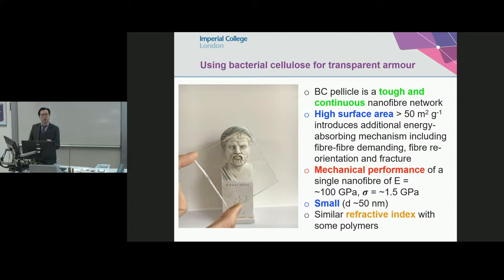And the diameter is small. Why is that good? It's so small that it doesn't interact with light, meaning it will be transparent if you immerse or impregnate it within the right polymer system. And lastly, it's the refractive index. The refractive index of these organic materials is fairly similar to that of some commercial polymers currently used for impact protection.